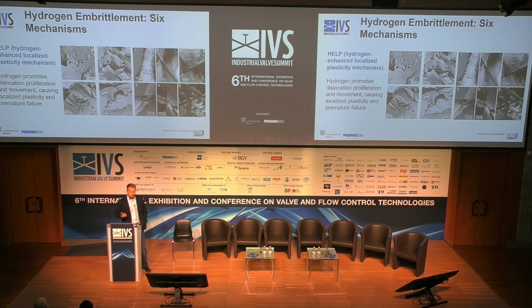This might be caused by a failed production mechanism, or by localized high or low temperature conditions and high pressure of hydrogen. I observed this one on a reactor. It was a low temperature, high pressure reactor, and we observed this kind of small bubbles that form on the surface. Once we did the analysis in terms of mechanical resistance, we saw that the plasticity was much higher than the rest of the reactor. So it was a simple fail on a localized spot.